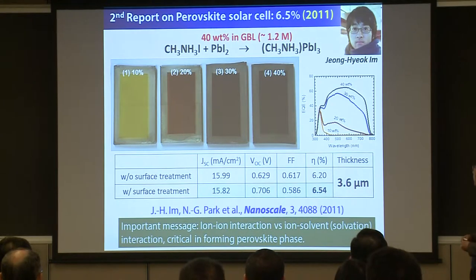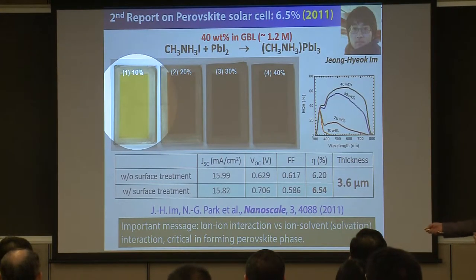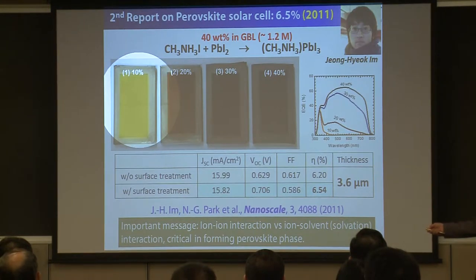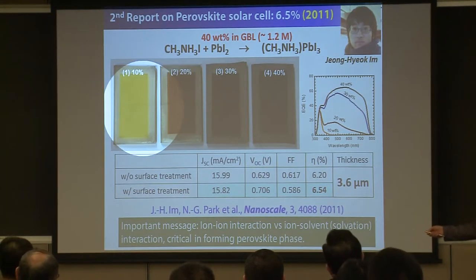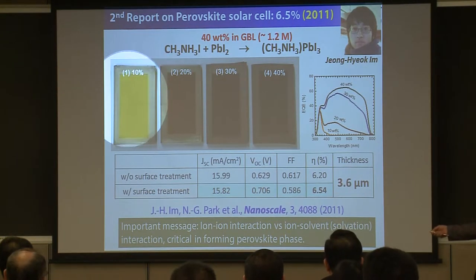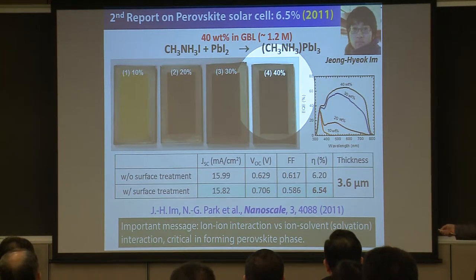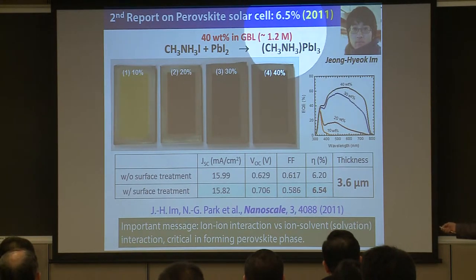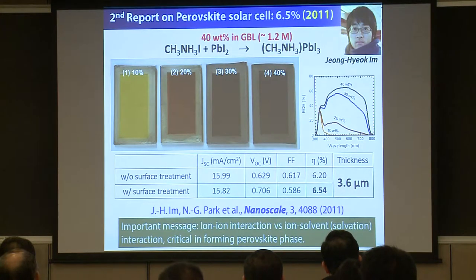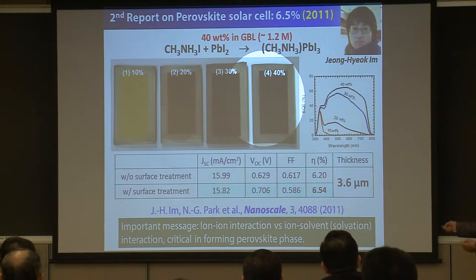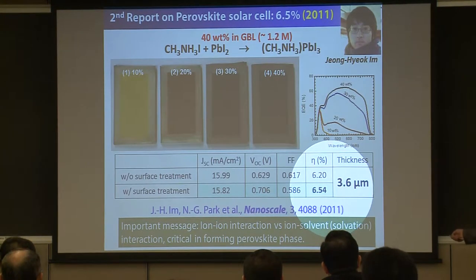So we resumed this perovskite solar cell. And Tsutomu Miyasaka actually proposed a 10 weight percent coating solution, but we could not obtain reproducibility by using his recipe. So eventually we developed a high concentration. This 40 weight percent is almost the supersaturation condition, which is about 1.2 mole. And now we use 1.2 mole or 1.3 mole as the coating solution concentration. And then we could reproducibly have the perovskite phase. And then we increased the efficiency to 6.5% with a much lower titanium oxide film thickness.